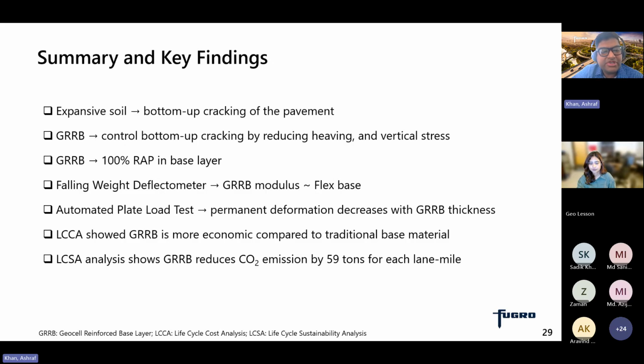Also, permanent deformation was reduced a lot. An Automated Plate Load Test proved that permanent deformation decreases with the increase in the GRRB thickness. That means if we use thicker geocell layers, we will have more design life, meaning performance will be enhanced. Life cycle cost analysis results showed that use of GRRB is more economical compared to the traditional base material.